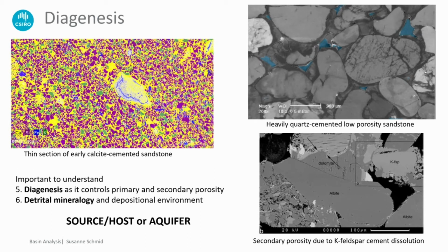There's nothing happening. However, if you have the right fluids hitting that calcite cemented sandstone at depth, and you wouldn't have much compaction because it's already as compacted as you can get it, with the mineralizing fluid, you can get dissolution going. So you're actually creating secondary porosity, which might help you to get your deposit forming at that time. So it's not necessarily a bad thing to have a highly cemented host in the beginning.